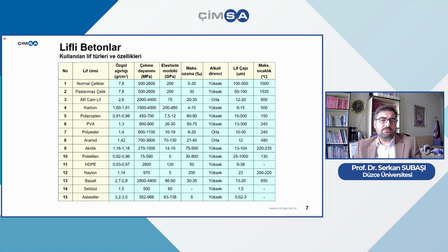Alkali resistance is not so good, and for this reason, when there is alkali inside the cement structure, it is causing a deformation, and it is causing the destruction of the structure. And for this reason, they are not widely used. When we speak about the alkali resistance glass fiber types, they do have more than 16% of an additive, and against the alkali environments, they are more resistant.